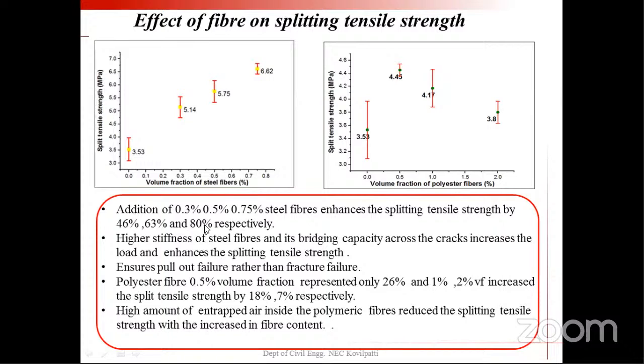It's a very, very favorable property, and one of the useful properties that can further be explored for performance based design. Higher stiffness, bridging across the steel fibers, is the main reason. It bridges across the cracks, increases the load and enhances the split tensile strength, and most of the failures were pull-out failures. There is no fracture failure.